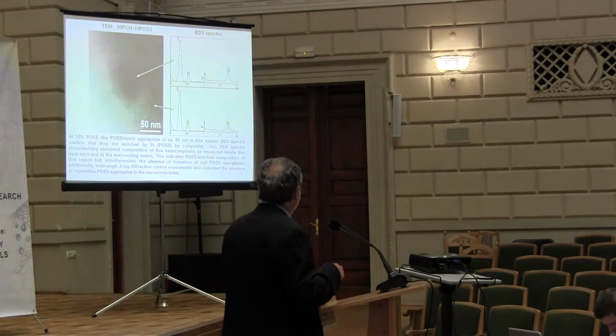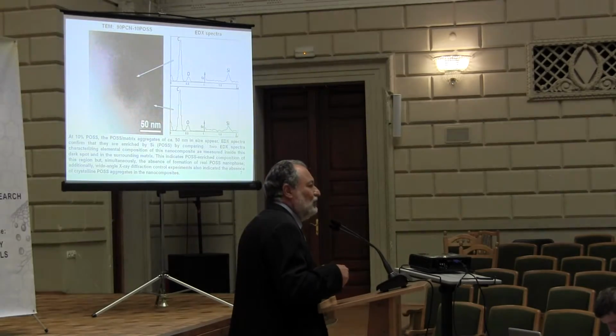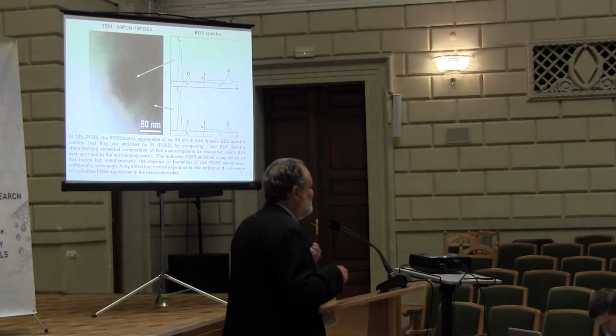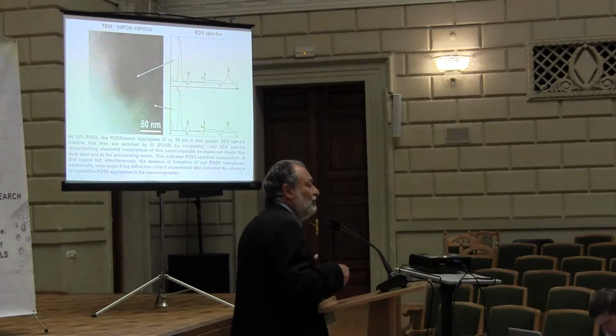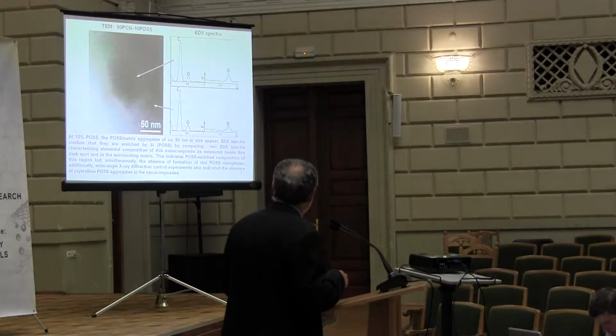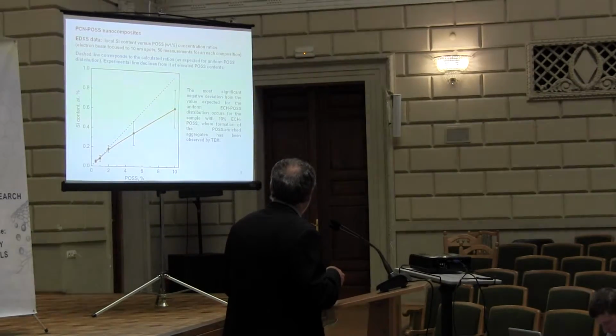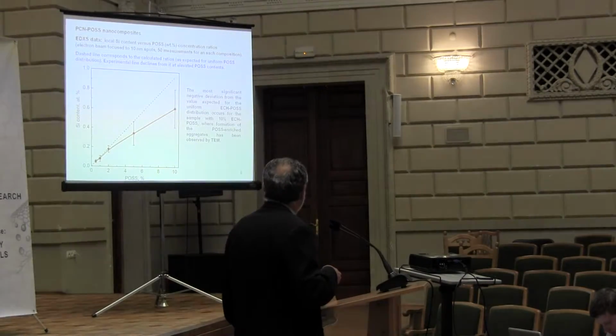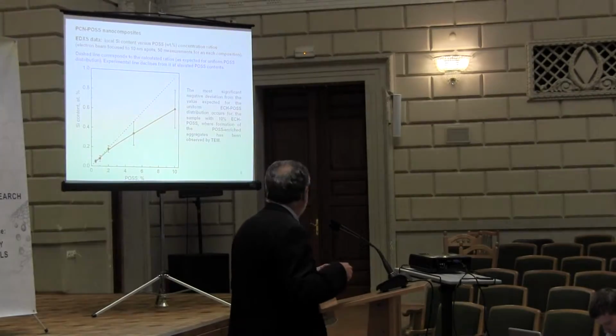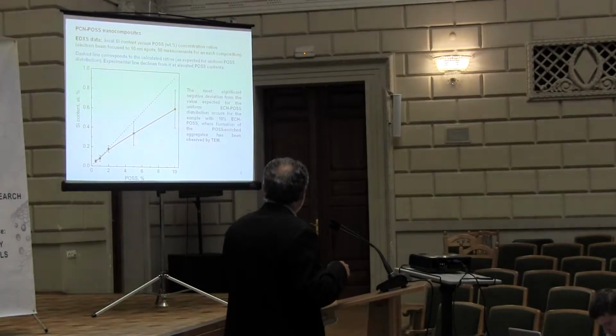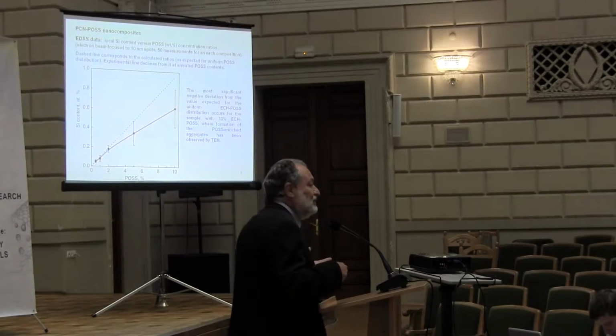we can say that the concentration of silica atoms is quite high in the dark zone, confirming the formation of the aggregates in this case. And here we have local silica content versus POSS concentration ratios. And the dashed line corresponds to the calculated ratios as expected for uniform POSS distribution. And the experimental line shows the experimental result.